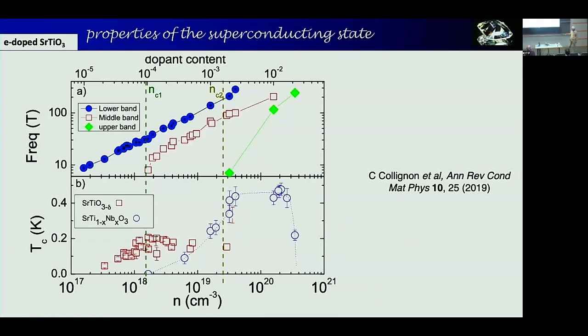And you find that there's a first dome and a second dome. Now you shouldn't forget, this is a dome on a log scale. So if you put it on a non-log scale, it looks very different from a dome actually, or it's a sort of distorted dome. But this looks like a double dome, and the speculation is that these domes probably have to do with the fact that you are filling different bands here, and that gives a bit more structure than just a single dome. That's the idea.